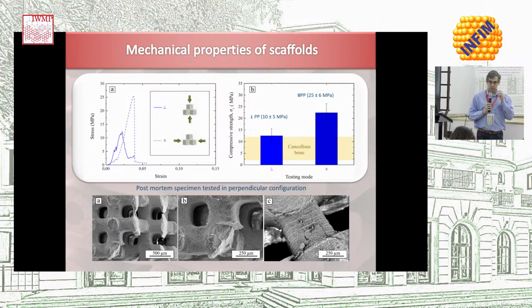What about mechanical properties? Because as Antonia mentioned, that's our main goal, to try to produce a scaffold with improved mechanical properties. And as you can see, the compressive strength of this scaffold is comparable to that of RoboCast structures, but there is a twist here, and there is a difference in the mechanical behavior depending on how you load those structures. They were supposed to be symmetric in all directions, but when you test the scaffolds, if you test loading parallel to the layers that you have deposited, your material has a much higher strength than when you test it perpendicular.